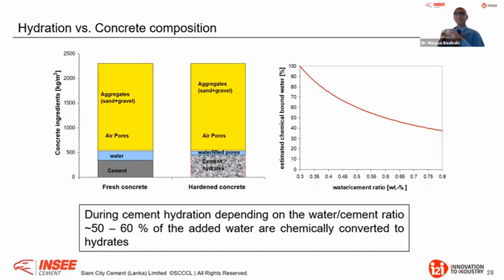But in reality, when we look at most of our applications, we are above this water-cement ratio. And this is what I call the workable water, water that we adjust to give us the possibility to mix and place the concrete. This will be very different from segment to segment in the application. When I look at the industrial segment, with more super-plasticized or more rational concrete production and delivery, we go more toward 0.4 and below. But when you go more to the retail or to grades of concrete below 30, the water-cement ratio should go more to 0.6 and above.